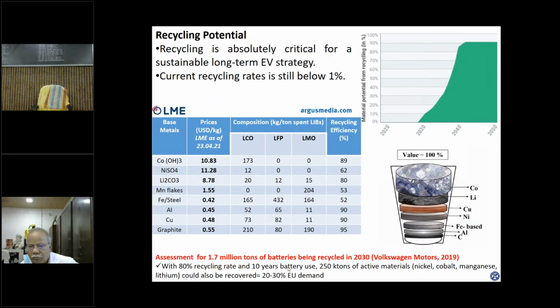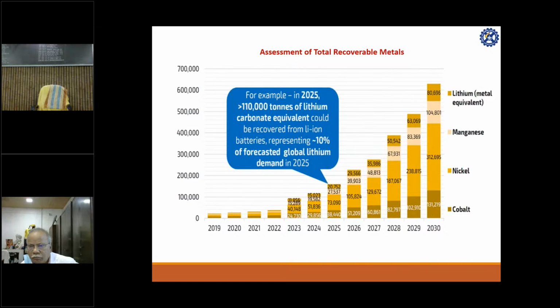So you can see, looking 20 years back, how this demand is going up. So everybody is thinking about recycling, and that's how recycling has to be there. Still, we have only 1% recycling occurring in the actual scenario. So when you do recycling, you have to have an assessment of total recoverable metals. At the moment it is very low, but when you add to this figure the current research and the commercial aspects and the transport scenario going on, you can see over here the maximum contribution, of course, is from the nickel part, because nickel prices will go up, followed by cobalt and lithium.